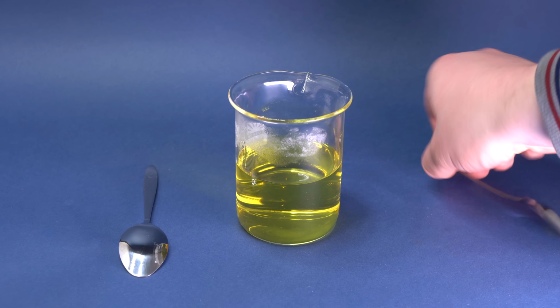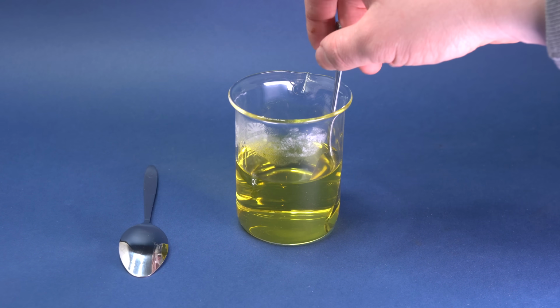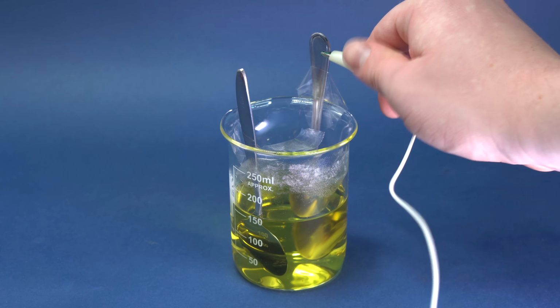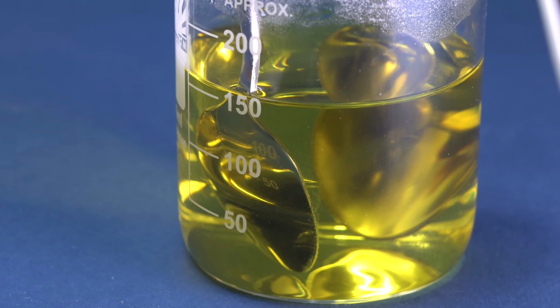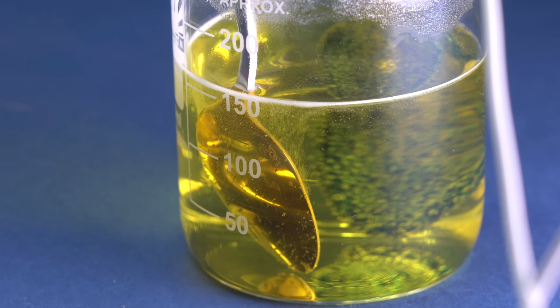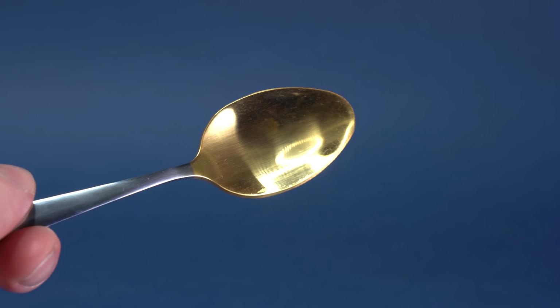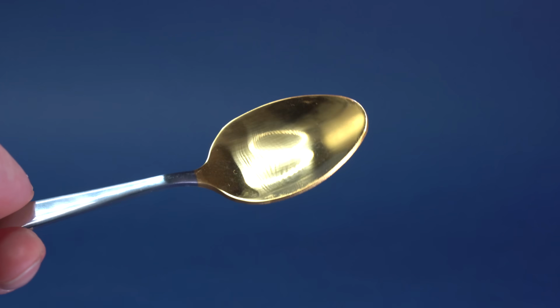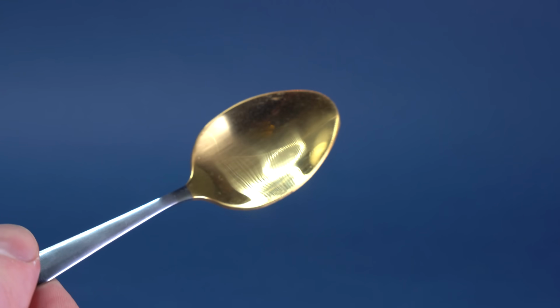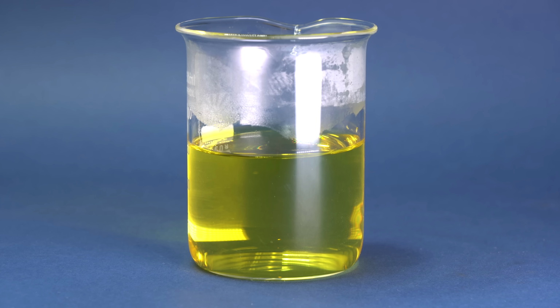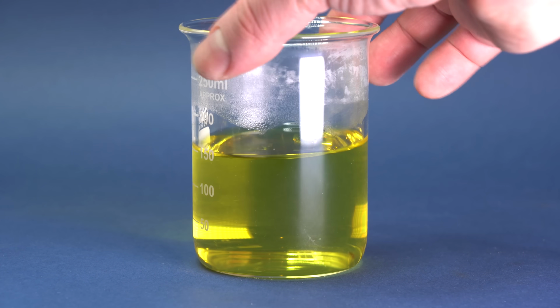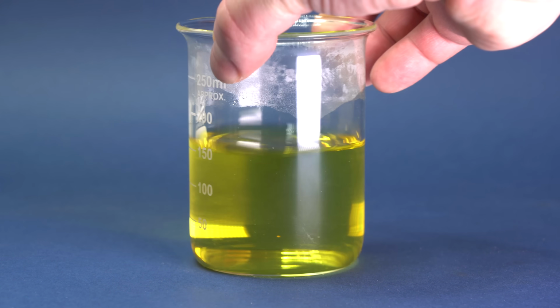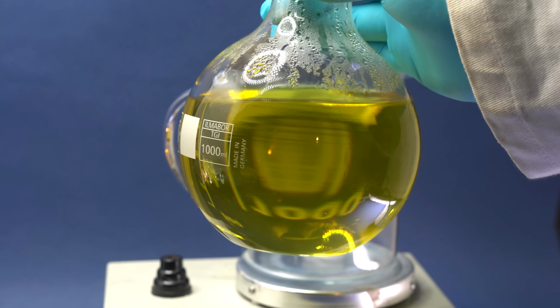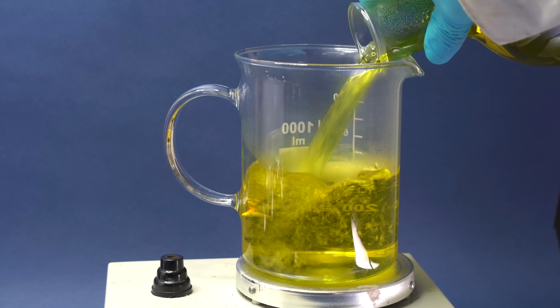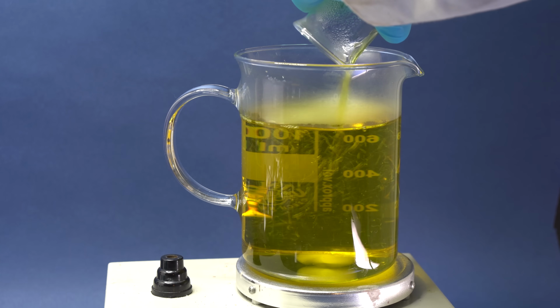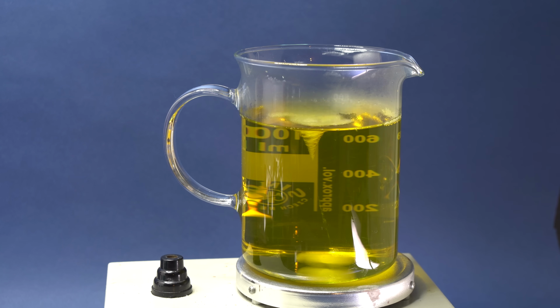To test my electrolyte, I took 2 steel spoons and connected them to the electrodes of my electricity supply. After that, I applied 3 volts and 200 milliamperes current. As a result, 5 minutes later, the spoon connected to the cathode was coated in an even and beautiful layer of gold. I think now my electrolyte is definitely ready for gold plating. Finally, I have made about 500 ml of electrolyte from 20 ml of chloroauric acid. Basically, everything is ready now for gold plating.